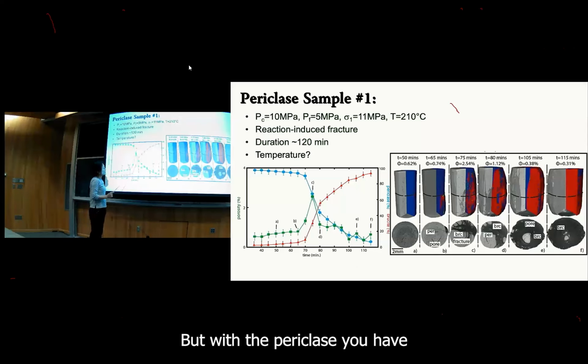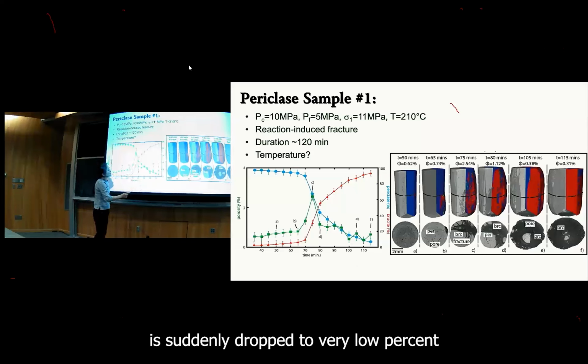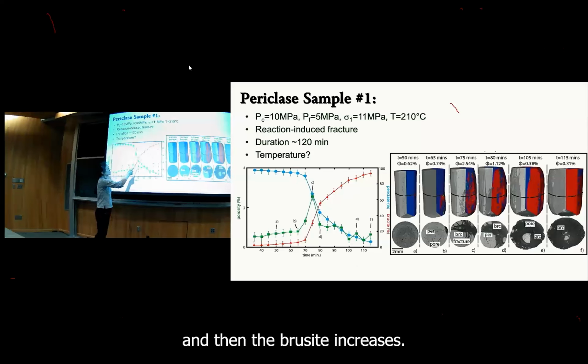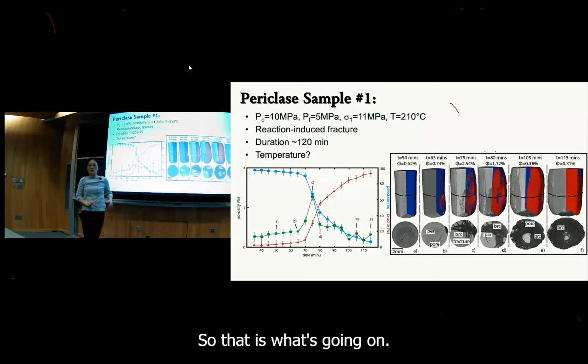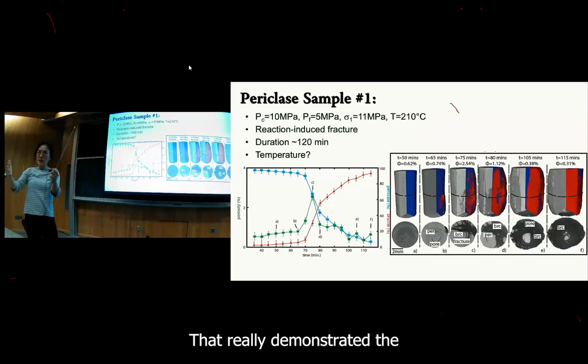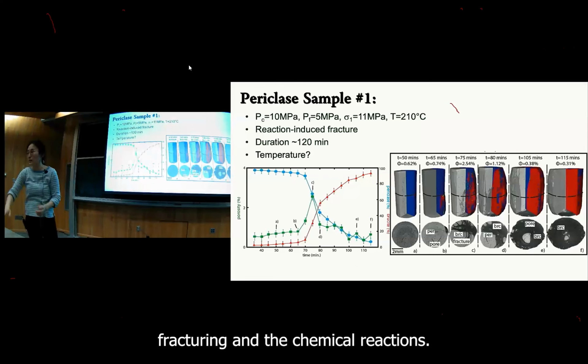But with the periclase, you have really accelerated chemical reactions, and all the periclase, the blue, suddenly drops to a very low percent, and then the brucite increases, all right? So that is what's going on. This really demonstrated the coupling between the mechanical fracturing and the chemical reactions.